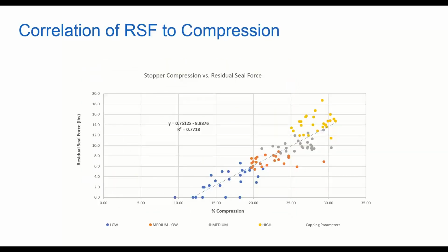So as I mentioned, residual seal force can help us determine how well the rubber is compressed against the glass. Here we see a correlation of residual seal force to the percent of stopper compression. In this particular work, what we did is used 4 sets of capper parameters, adjusting those parameters to increase the compression, and then we can see a corresponding increase in residual seal force. And you'll see a little later why this becomes important.